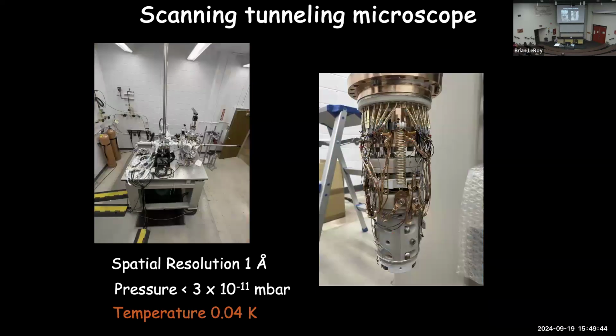But recently, we've upgraded to a new microscope here in the lab. Here, we keep the same spatial resolution and same pressure in the system, but now we've lowered the temperature down to 40 millikelvin. So this basically gives us a factor of 100 improvement in our energy resolution. We go from basically 1 millivolt down to like 10 micro eV. We just got this system up and running a couple months ago now. And hopefully we're going to get some very interesting new results by being able to probe even lower energies